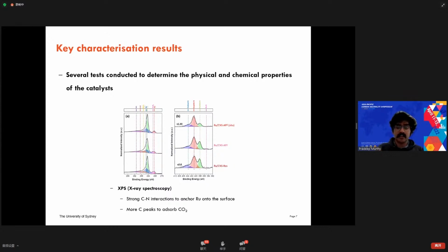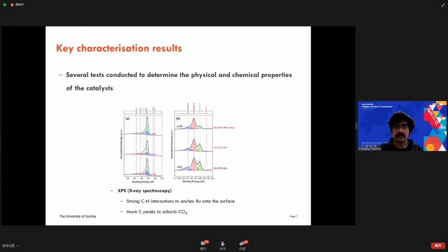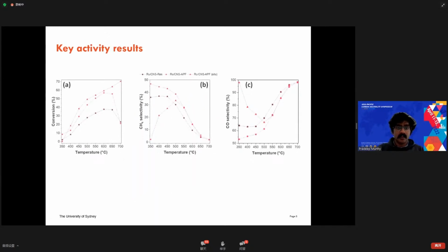And finally, XPS indicated more carbon-nitrogen interactions, which would help both to anchor the ruthenium onto the surface and also enable more carbon dioxide absorption over the catalyst surface. That way we get a more hybrid system between the ruthenium and the carbon-nitrogen, which can enable more reactivity from easier H2 dissociation and CO2 absorption.